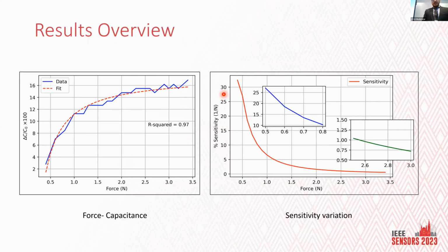So these are some results: force versus change in capacitance. If you increase the force, as I told you in the first slide, there is an inverse relation between capacitance and force. So this fitted line is for the inverse relation of the capacitance, and this is how we derive the sensitivity and its values, which I will come back to in a later slide. So this is the sensitivity change with respect to force. In the low force regime, it is very highly sensitive, and if we apply more force, we get lesser thickness and lesser sensitivity.